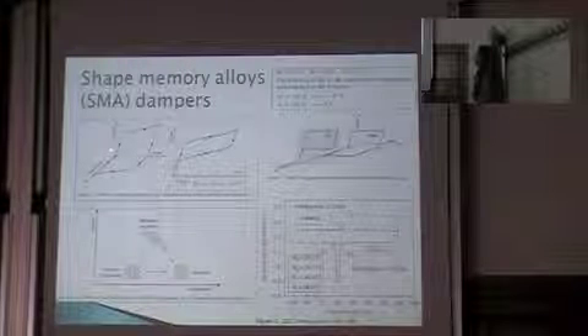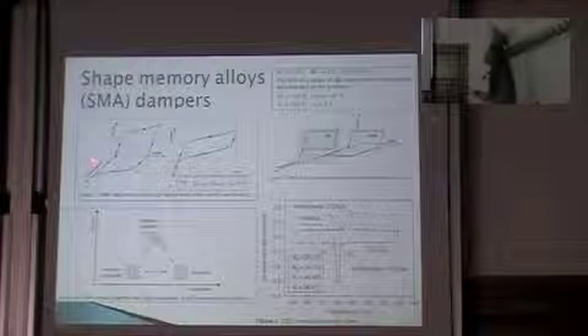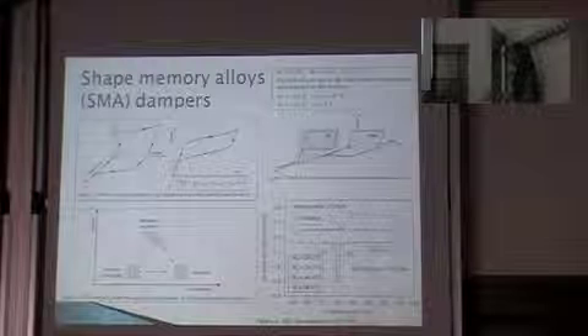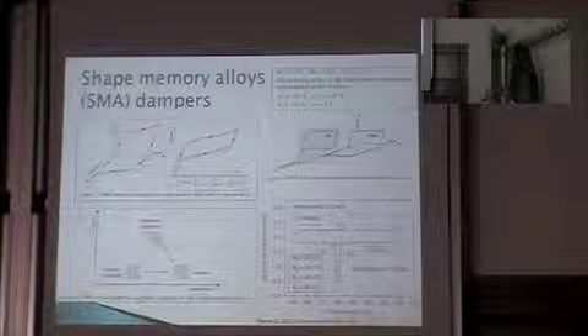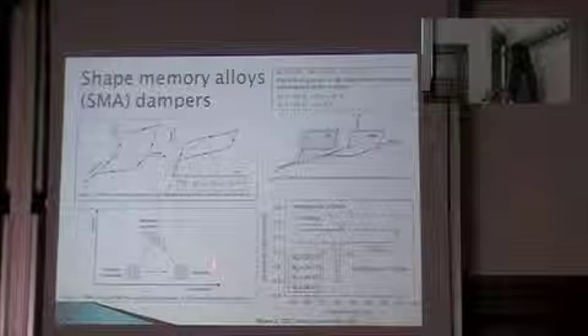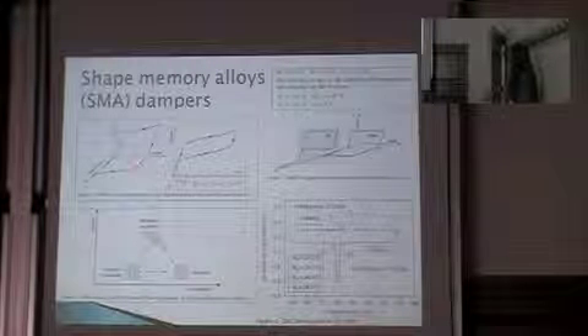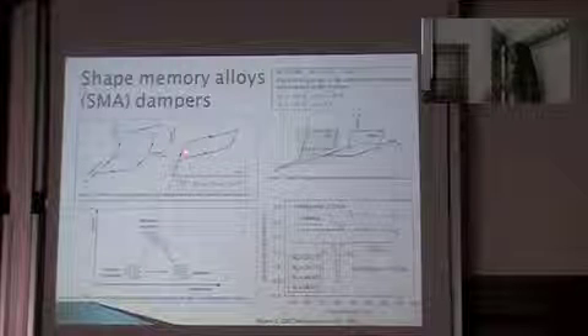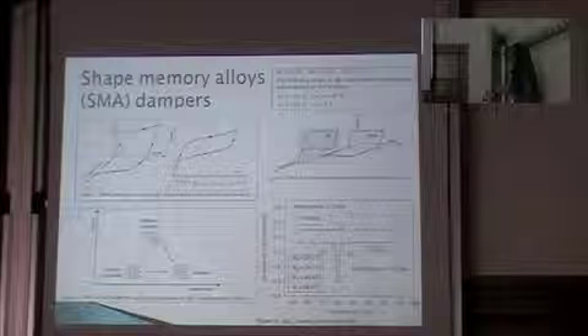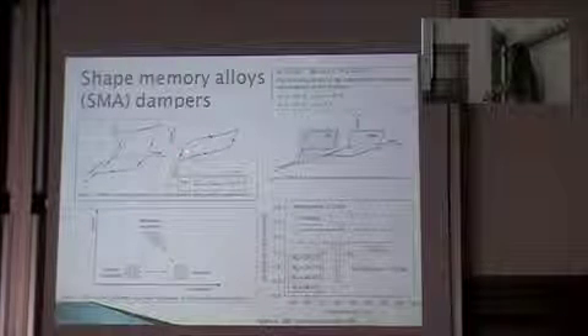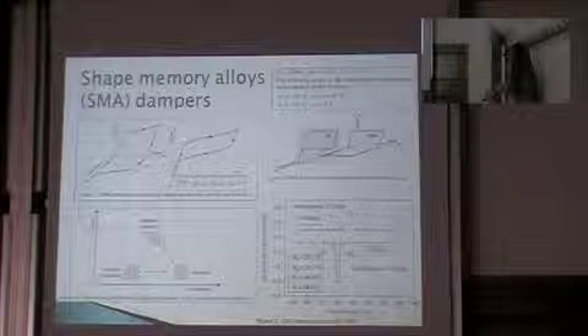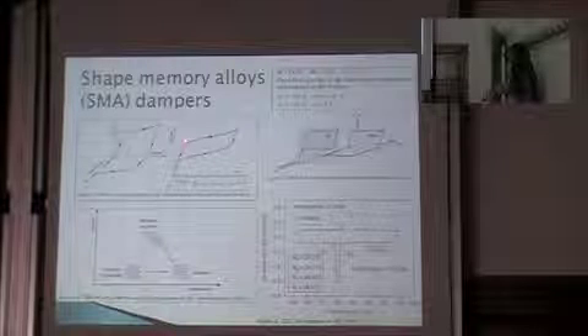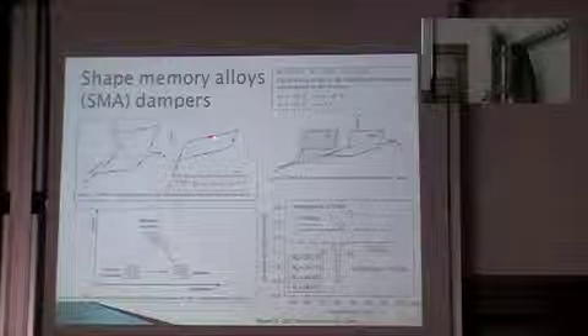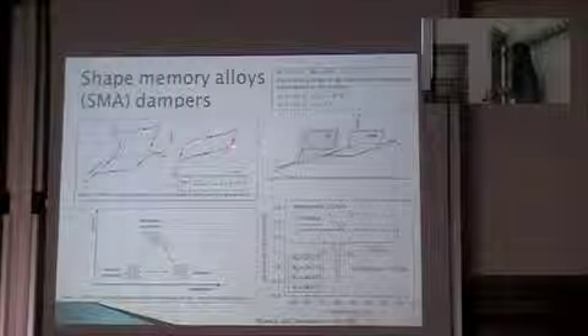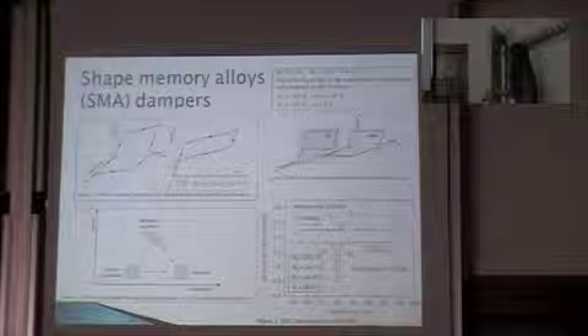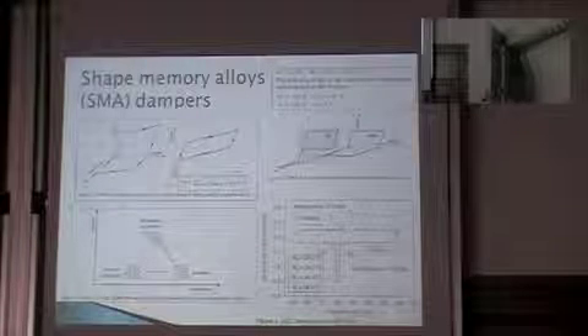This heating causes a stress, which is the actuating stress that can be used for actuating at low levels of forces, of course. Whereas when we are in the austenite phase, during the loading, there is the mechanical transformation, no longer the thermal, in which the austenite, the initial elastic phase, then starts turning into martensite, and we have this increasing plateau, and then during the unloading we have the inverse transformation. As a result, we have a loop whose area can be used to dissipate energy and be transformed into heat.